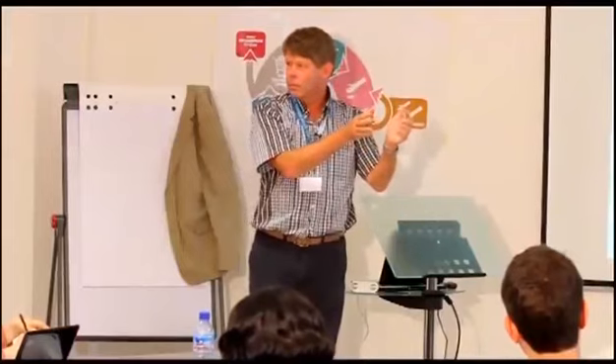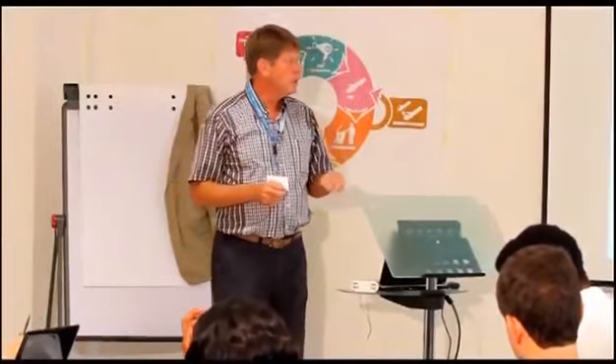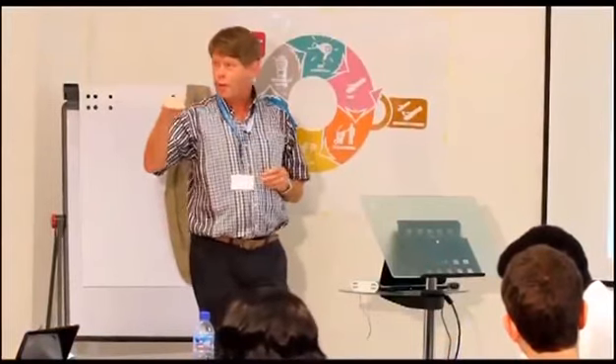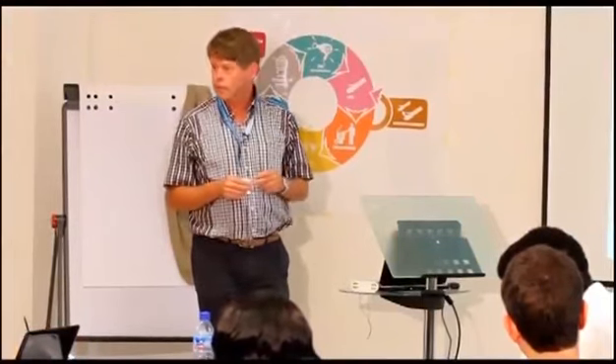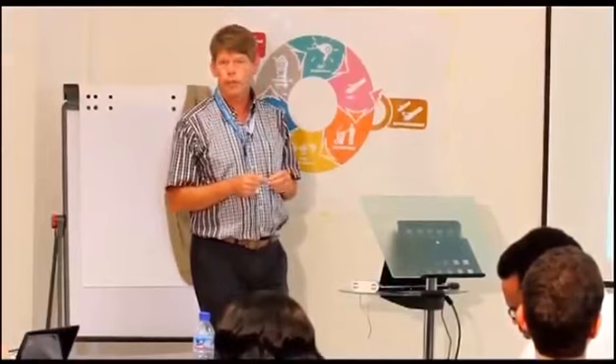Of these 15, there are a few that are really restricted. I mean, like POPs, persistent organic pollutants. And that discussion is currently going on for Penta and for Octa BDE, which is a bit of an issue. We are talking with some authorities and some studies that are being made that want to reduce the thresholds to 100 ppm of these sort of materials. The problem with 100 ppm is that the recycling industry cannot guarantee 100 ppm, and we cannot even measure it to that extent. So that's the problem again. Currently, the threshold level for that sort of substances is still 1000 ppm, which is perfectly fine. We can live with that.